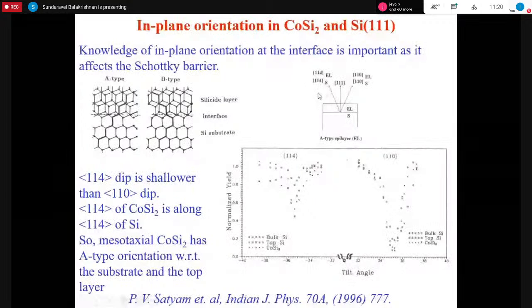And for seeing it, what we do is for the substrate, we stay in the 110 plane, and in the 110 plane, if you tilt by 35.26 degree from 111, you see the 110 direction. That is the deepest planar dip, the deepest actual dip. And in the other direction, if you tilt 35.26 degree, you'll be seeing 114. That 114 won't be as deep as 110. It will be shallow.